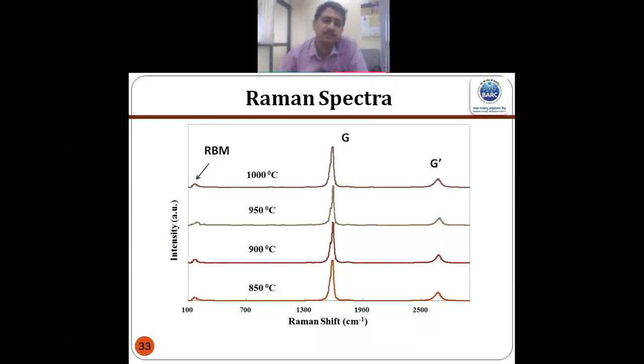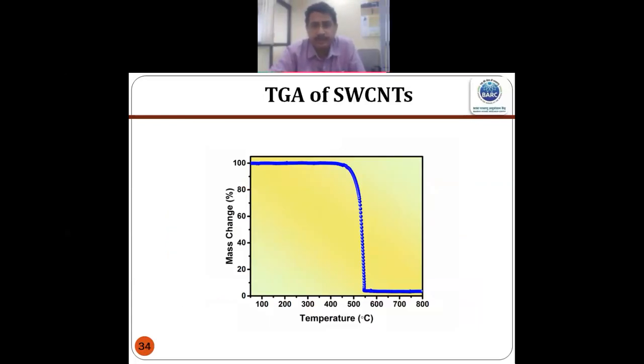Now the typical Raman spectra. Here you can see the D has almost vanished. Here the D is not there. Instead of that, you get an RBM peak, that is called radial breathing mode, from where we can get the diameter of the carbon nanotube. We can calculate that. And in TG also, you will get a very sharp drop. So no two peaks. If you take the differential, you will get only a single peak.